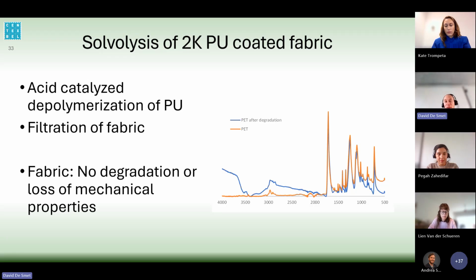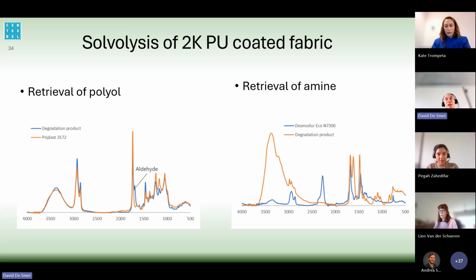Just at the right, you can see the infrared analysis. Again, you can see that the peaks are quite the same, so there's no chemical degradation or hydrolysis of your polyester during the recycling process. Of course, in the case of chemical recycling, it's also important to retrieve your polyol and your isocyanate compound. Therefore, we also had a further purification of the different degradation products. And actually, we could retrieve both the polyol as well as the amine, which is derived from our isocyanate.